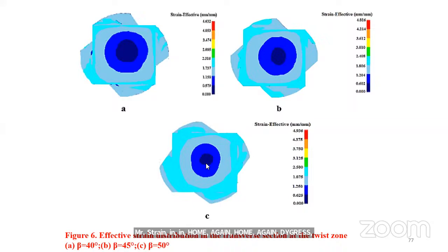You can see that at 50 degrees the intensity of the strain distribution is more when compared to the other two angles. That is 4.6, 4.8, and 4.9. You can see the effective strain is 4.9 here. So beta is equal to 50 degrees, where beta is the slope angle. 50 degrees produces very good strain homogeneity, so we have selected this parameter.